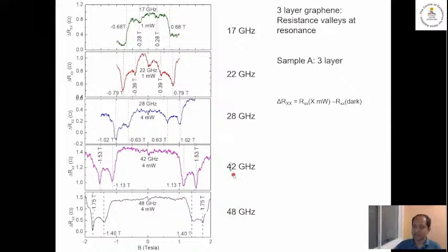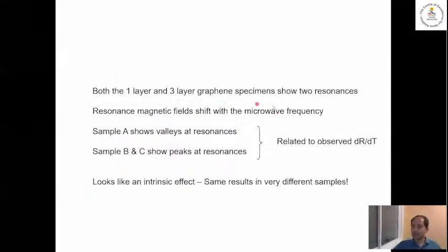We can change the frequency from 48 to 42 to 28, 22, and 17. As you change the microwave frequency, the resonance moves to lower magnetic fields, both of them, both the positive and negative magnetic field. Okay, so both 1 and 3-layer samples show 2 resonances. The resonance magnetic fields shift with the microwave frequencies. The first sample showed valleys at resonance, and the 2 other samples showed peaks at resonance.